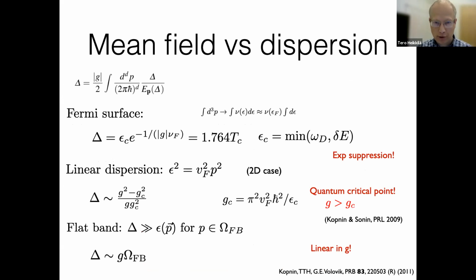There are a few generic limits where you can do this. The most common one, and the best known, is the Fermi surface case, where there is a logarithmic divergence in the BCS gap equation, and you need to cut it off somehow. As a result of this cutoff, you get an exponentially suppressed delta. This is the form of the BCS delta versus the coupling strength G, where the prefactor is the cutoff energy, which for electron-phonon coupling is typically the Debye energy, but for flat bands could also be just the bandwidth. The bottom line is that you have an exponentially suppressed energy scale compared to the microscopic energy scales in this system.